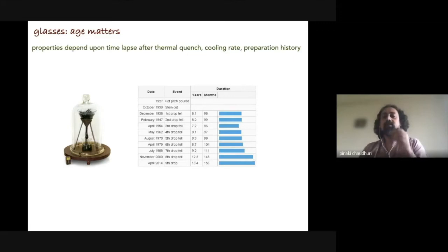If you look at the time scales elapsed between the two drops, you see that the interval has been increasing as the age of the system grows longer and longer. For example, earlier on it was 98 months, but in April 1979 it's 104 months, and in April 2014 it's about 156 months. So basically, the observation of any event takes longer as the system becomes older and older.